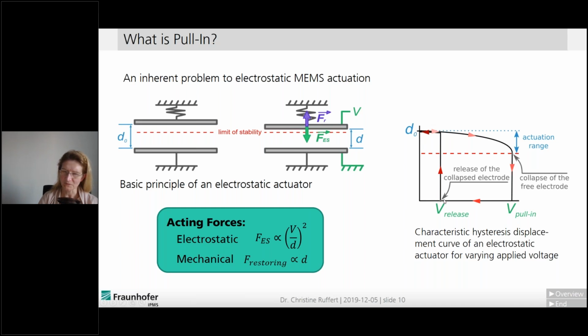Here's the cycle of this configuration. When you start at a distance d0 and apply a voltage, written on the x-axis, the upper electrode will bend down and approach the bottom electrode, and at a certain point the electrostatic force will exceed the restoring force and the upper electrode will collapse. This is indicated as the limit of stability in this design, and you can see it in the graph, indicated by the red line. Then you have a pull-in, so the two electrodes collapse and nothing happens anymore. With a bit of luck, you might cause a release when you go back with the voltage, but normally you have to apply real mechanical forces to separate the electrodes from each other. With our system, we don't have this problem, and I will show you why.